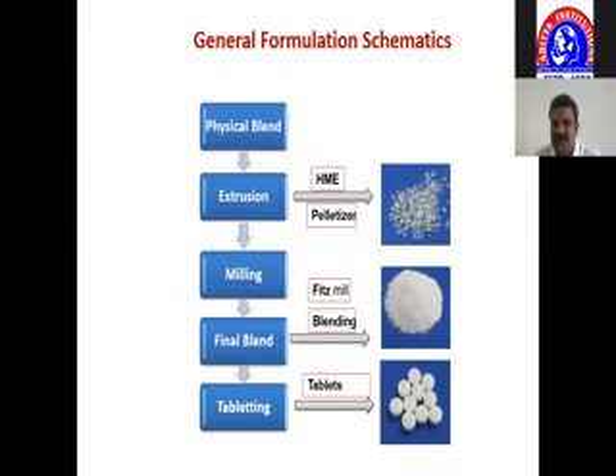This is one of the general formulation schematics. You take a physical blend of a drug and the polymer. You perform extrusion. Once the extrusion has been done by an HME method, what you get is pellets. These pellets are further milled down using a suitable mill. You get a powder or granules. These granules, along with extra granular material, you convert into tablets. Now you see the pellets are more of a glassy shape in nature. This glassy shape indicates it's a solid solution. That means you have converted a crystalline material to an amorphous form, and thereby you have enhanced the solubility of the drug.